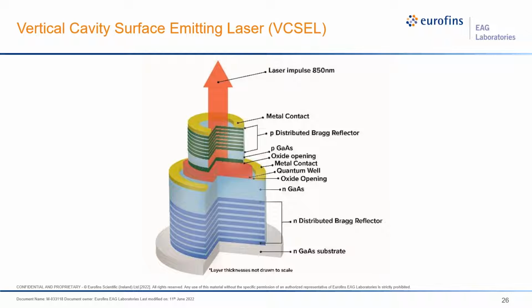To produce high-performance VCSELs, the DBR is formed from alternating layers with sufficiently high refractive index contrast to realize high levels of reflection. Engineers must also ensure that the conductivity of the mirrors is sufficiently high to prevent excess ohmic heating when injecting current into the active region. High-efficiency VCSELs are possible when these mirrors form a part of a structure with a high degree of optical and electrical confinement. Such a device may be built from more than 200 layers, some of which contain grading of both the dopant level and alloy composition.